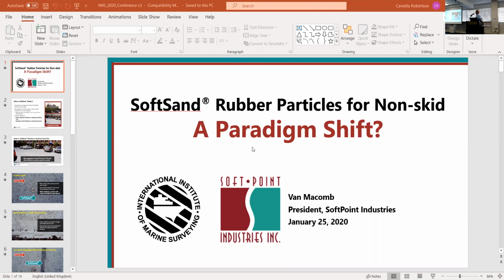So the practice that's evolved over the years with that understanding is that if you read some of these data sheets, they recommend using as little as possible to create a non-skid surface. I've seen some recommendations as light as 3 ounces per gallon of paint, which is not very much. And if you look at the particle size they recommend, it's often 60, 80, 100 mesh. It's a very fine particle.